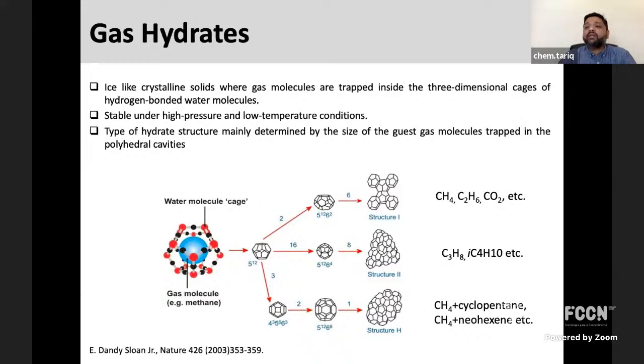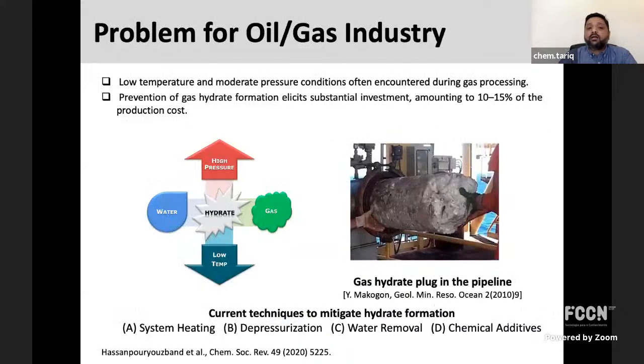There are three different types of gas hydrates: structure 1, structure 2, and structure H, which mainly depend on the size of the polyhedral cavities and the size of the gas molecules. For example, methane, ethane, and carbon dioxide can form structure 1 hydrates. Propane and isobutane can form structure 2, and complex mixtures like methane and cyclopentane, and methane and neohexane, can form structure H type of hydrates.